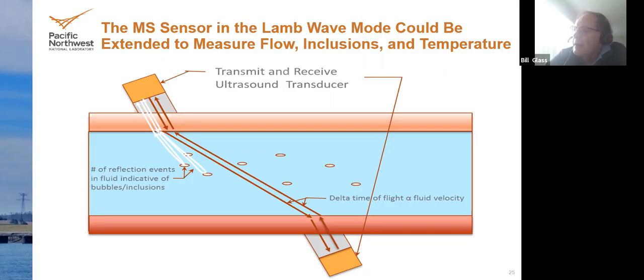This is an application where we're trying to adapt a magnetostrictive material to see flow in a pipe, and that's done by looking at the differential time of flight from the transmitter to the receiver, and we send it both ways and look at it differentially, and that is proportional to the mean velocity of the material in the pipe. That's pretty important. Flow measurement in these advanced reactors is an important criteria that's darn hard to do at these kinds of temperatures.